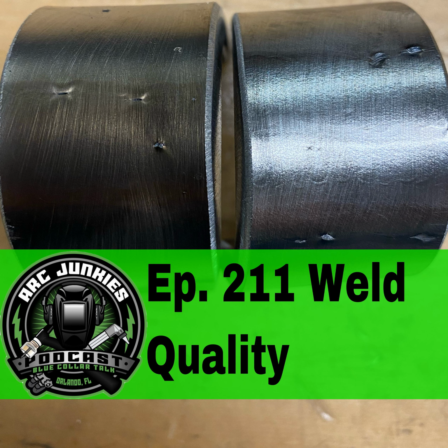So if I put like a flush root in there, and it looks all nice and clean, by the time I go to put my hot pass on there, it can start pulling those pipes together, and it can pull that weld back into the side that I'm welding on. So now I've got underfill or suck back on the inside of my pipe or the back side of my plate, and you don't want that in there. That's the concave root surface. To avoid that, make sure you're watching your travel speed. Make sure, once again, you prep your joint properly and maintain a good tight arc length, and that should help alleviate that.